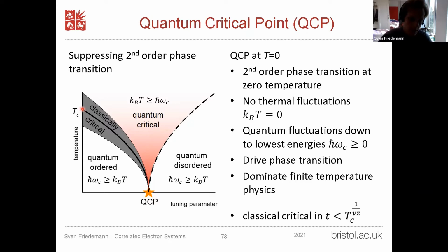And I'm here talking about second order phase transitions. Actually, on the previous slide, I was also talking about second order strictly, because otherwise there would be a finite energy between the two states, and all of what I've said would not apply. Okay, so tuning down that phase transition means that the range that is classical around it must also become smaller, because kBTC, the thermal energy that's available right at the transition, becomes smaller, and hence there's less energy available for large patches to fluctuate between the two states.